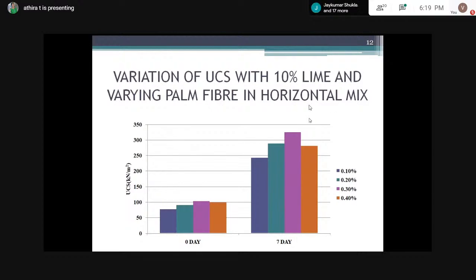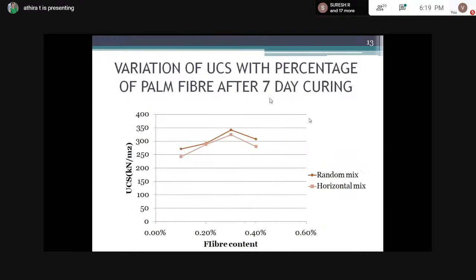And going on to the results for horizontal mix, we can see that up to 0.3% it showed an increase in the value, but for 0.4% it shows a decrease. And here also 7-day cured sample is better in improvement than the 0-day cured sample. Now, comparing the results of horizontal mix and random mix, we can see that the random mix sample is much more effective in improving the soil than the horizontal mix. This is for the peak strength.